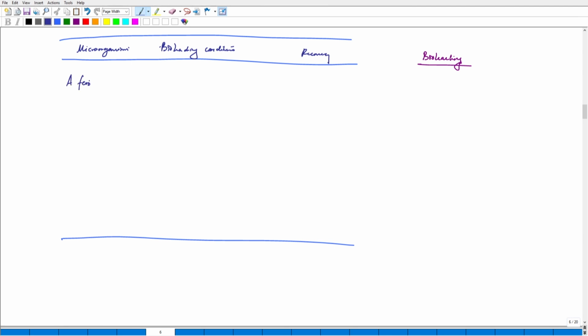A. ferrooxidans. So in this case, one has to actually mention as much as possible what is the size. This is the size of the WPCB actually. So 93 micrometer, pH is 2, 17 to 20 days, because one has to keep it for a very long period, 80% copper recovery. Similarly, if you have 178 to 250 micrometer size, pH again is 2.25. They kept it for 183 hours, and Fe2 plus addition is, let's say, 9 grams per liter. You get 92% copper.